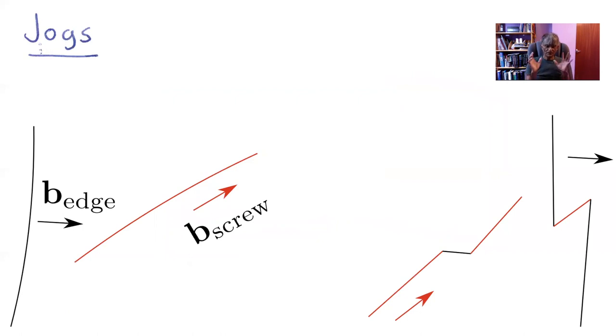Okay, so we've discussed the structure of an interface in terms of dislocations. And in general, for a general interface, you'd require three independent sets of dislocations to completely accommodate the fit between the two abutting crystals. Okay. So let's just think about that a bit more. So if you looked at it in a transmission electron microscope, you would see three arrays of dislocations in general.